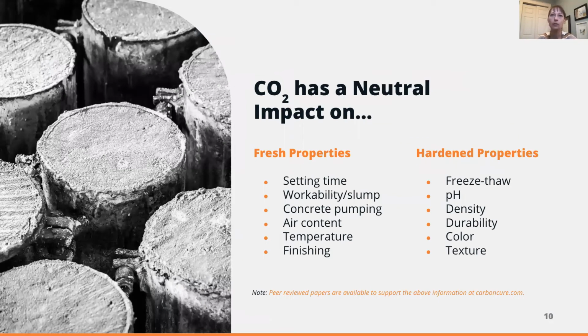The CO2 has a neutral impact on the fresh and hardened properties of concrete. There have been many, many studies conducted by academics, by third-party organizations, such as in the United States, departments of transportation, that verify these statements that the fresh properties, the set time, workability, concrete pumping, air content, temperature, finishing are unaffected by CO2. Hardened properties, freeze-thaw, pH, density, durability, color, texture, again, unaffected. In fact, some studies are indicating that there are certain durability properties that may be improved through the use of CO2.